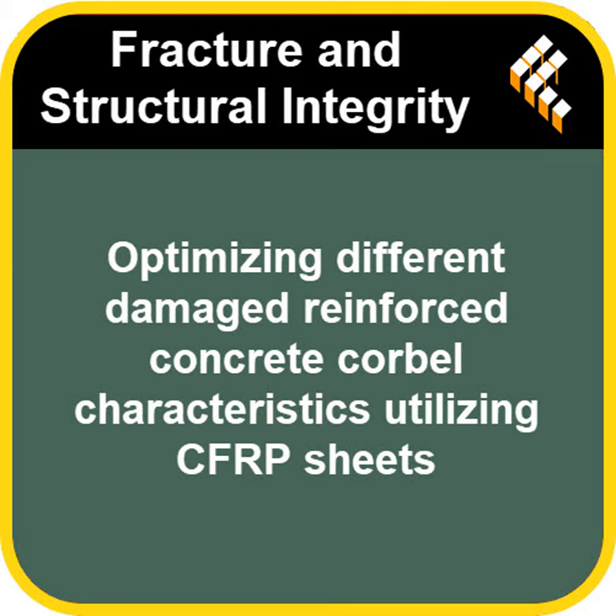Okay, so let's quickly summarize the big takeaways from our deep dive today. Sure. I'd say first, CFRP strengthening significantly increases both load capacity and stiffness of concrete corbels, whether undamaged or moderately damaged. And side wrapping generally outperforms strip wrapping, especially for damaged elements. Correct. Second, there appears to be a critical damage threshold, probably around 50% or maybe a bit higher, beyond which CFRP repairs offer much less benefit in terms of strength gain. Early intervention is key. Got it.